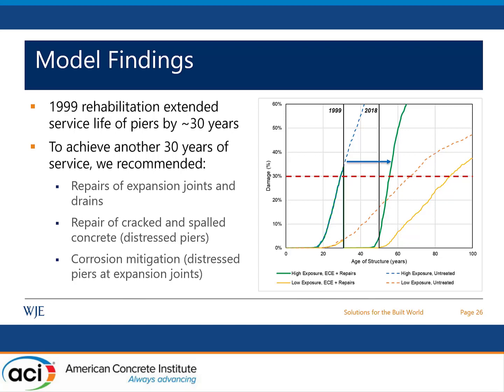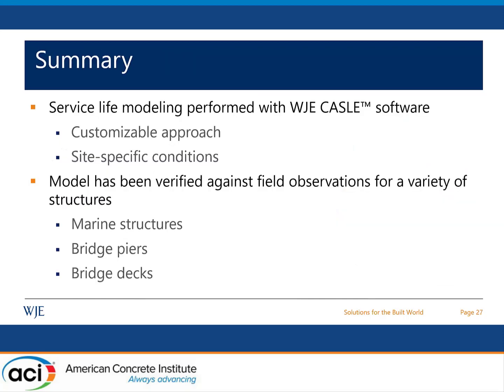So we recommended to the DOT that they perform repairs of all of the expansion joints and drains to help limit some of those chloride exposures. We recommended repair of cracked and spalled concrete in those particularly distressed areas of the piers. And in the piers that were distressed and located at expansion joints, we also recommended additional corrosion mitigation.